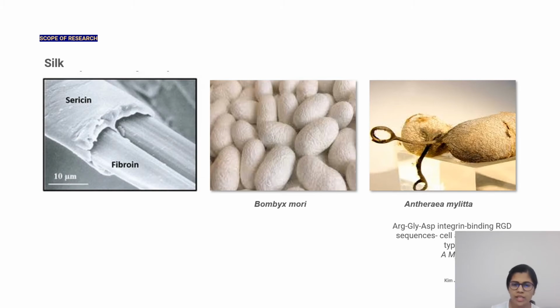Two types of silk variants, Bombyx mori and Antheraea mylitta, are being considered in our study. The main reason for selecting these two silk variants is to compare, because Antheraea mylitta, which is a wild variant, consists of arginine glycine aspartic acid. This particular ligand, the RGD sequence, actually helps in better cellular interactions and mineralization.